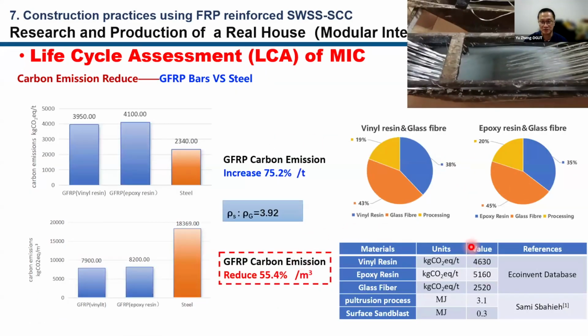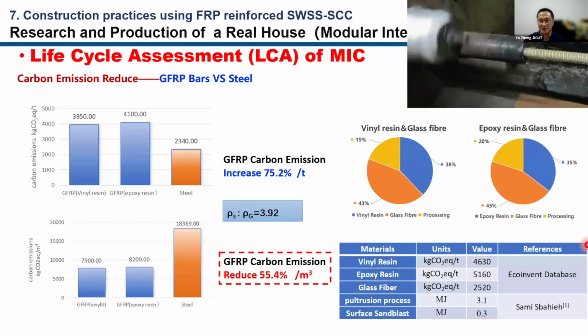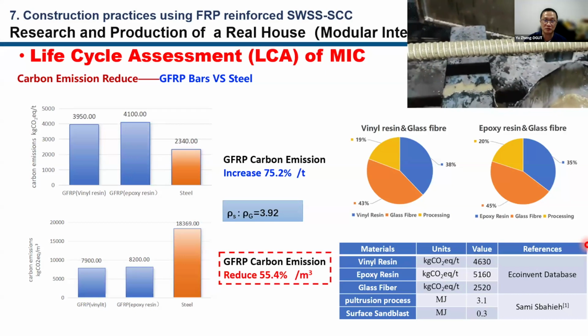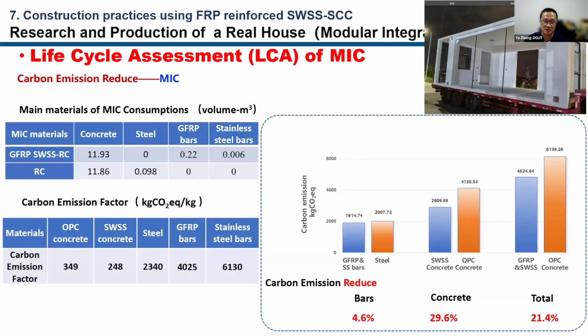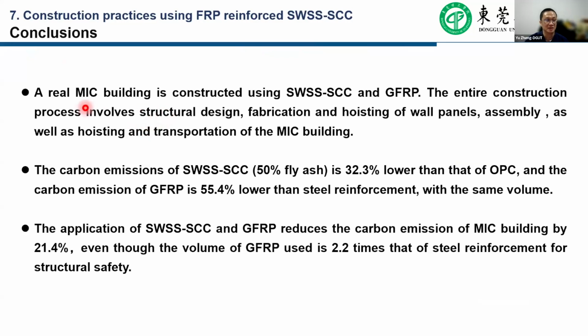I will make some final conclusions. After the analysis, we can find that with the GFRP reinforced seawater and sea sand slab compared to the steel reinforced ordinary concrete, the carbon footprint can be reduced by more than 20%. The real MIC building was constructed using seawater and sea sand self-compacting concrete and GFRP, and the fly ash content is quite high, and therefore we can reduce the carbon dioxide footprint. Furthermore, this construction method can reduce the carbon emission compared to the steel reinforced concrete structure by more than 20%.